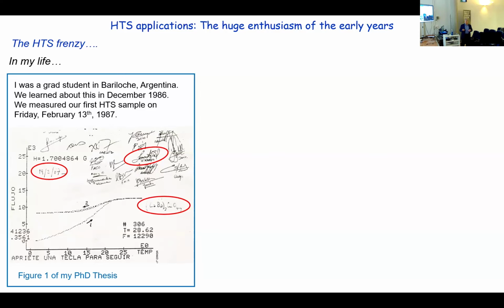So suddenly I was interested in this. We measured in our squid magnetometer. This is an attempt to see something like a Meissner effect. And so we put the sample, increased the temperature. We saw that the diamagnetism was disappearing. Then it got flat, and then we cooled down again, and we saw real expulsion of field, which is very indicative of superconductivity. At that time, it was about midnight. We were totally excited about that.